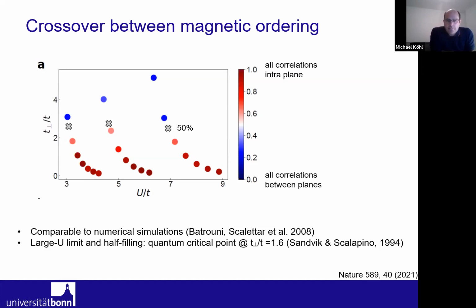interplane tunneling matrix element. This number, surprisingly, is not that far away from the prediction of the quantum critical point, which is at 1.6 for the large U limit. And it's also comparable to other numerical simulations, which mention a value in the range of about 2. We can say that we see the expected behavior here for this crossover between these two magnetic phases.